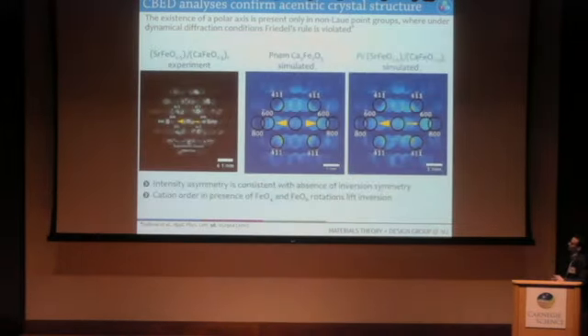So this is the experimental intensities, so the 6 bar 00 and the 600. If the structure has inversion symmetry, the intensities should be identical. Here, the contrast is quite opposite. And they perform simulations which mimic this effect.